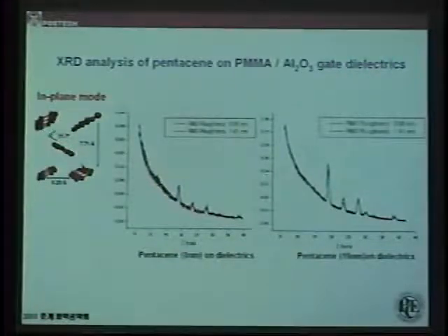The first peak is the closest, which is the diagonal direction, the way the hole is moving. The second and third peaks are this horizontal direction, the herringbone structure. The fourth and fifth peaks are this vertical direction, with much longer spacing.